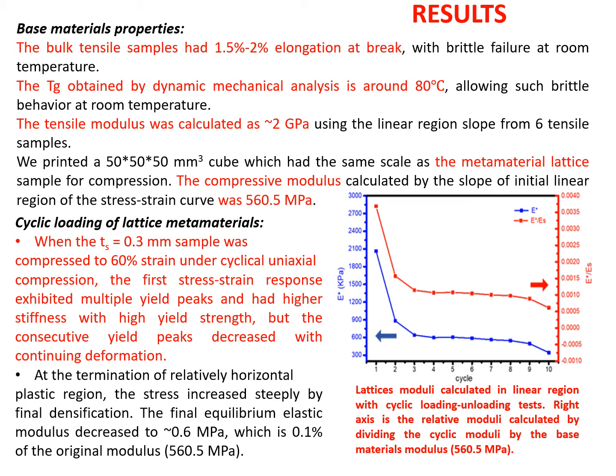The compressive modulus was measured as 560.5 megapascal. As far as cyclic tests, when the 0.3 millimeter strut thickness sample was compressed to 60% strain, the first stress-strain response exhibited multiple yield peaks and had higher stiffness with high yield strength, but the consecutive yield peaks decreased with continuing deformation. So the elastic modulus also decreased, as shown in the graph on the right.